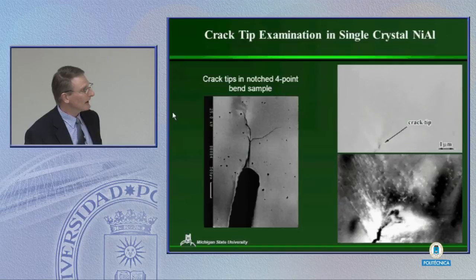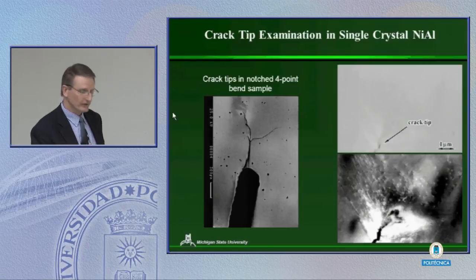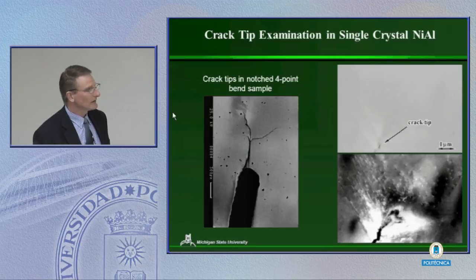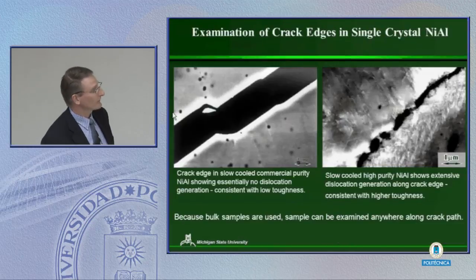Also what happens is as the beam comes very close to the edge of the sample, some more backscattered electrons leak out the side, which gives us increased intensity. But the critical thing is really what's occurring out here, in terms of being able to directly measure that plastic deformation field out in front of a crack.